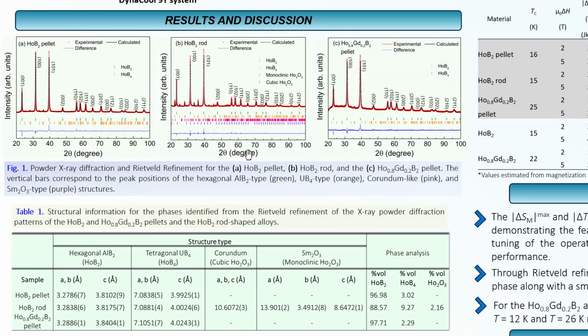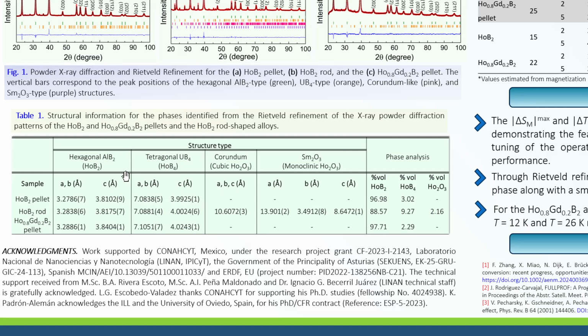Starting with the structural results, as we can see in Figure 1, X-ray diffraction confirmed that holmium diboride is the main phase in all samples, with holmium tetraboride detected as a secondary phase. In the case of the suction cast rod, small amounts of holmium oxides were also identified. And here in Table 1, we see that the lattice parameters obtained are in good agreement with those reported in the literature. Additionally, we see here the phase composition of each alloy.